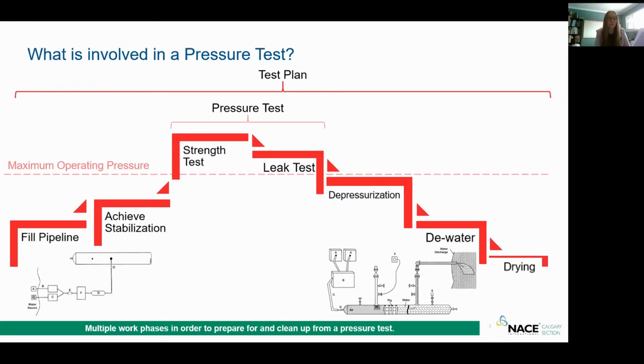So you get to your target test pressure, and this is where you call in the phase called strength test. This period really proves that the pipe can contain the pressure that it's rated for. Next, you move into the leak test. It depends spec to spec, but I recommend a slight decrease in pressure to get to the leak test. What this really means is it's a containment of volume still at minimum pressure greater than the MOP. So once the pressure and temperature are constant, what you'll get is this locked-in phase, and that's when you know you have a successful test on the leak test.